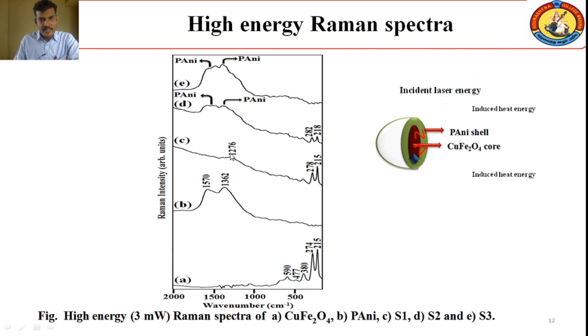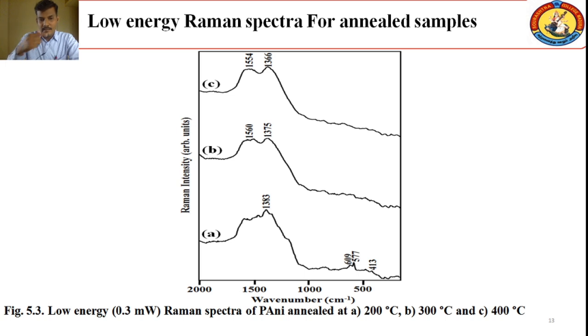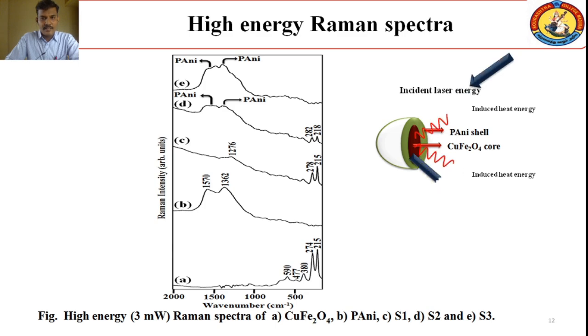Similarly, when we take the high energy Raman spectra for S2 and S3, there is also a change in behavior, a totally destroyed polymer chain, which confirms, but in this case here you can see the copper ferrite characteristic behavior, which confirms the core is present inside, and the polymer is very weak, that's why the laser can easily penetrate the surface. To confirm this induced thermal energy, we took Raman spectra for 3 different annealed samples. Here also you get the same characteristic behavior, almost nearly the characteristic behavior we receive from the high energy Raman spectra.